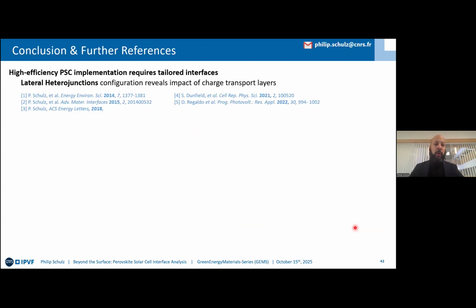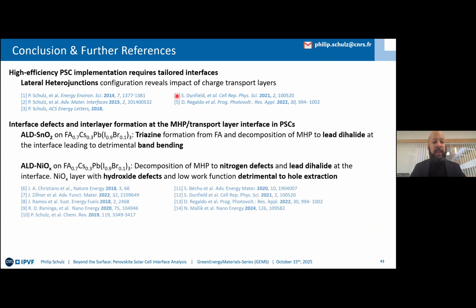To conclude, today we were talking about high efficiency, so the need for tailored interfaces to implement perovskite solar cells. We have this lateral heterojunction platform that reveals the impact of charge transport layers, and that we now use as an experimental platform to check different interlayers. We were looking into interface defects and interlayer formation of this halide perovskite transport layer interface in perovskite solar cells. When you deposit ALD tin oxide on top, we find this triazine formation from formamidinium and decomposition of the metal halide perovskite into lead dihalide, which is then going hand in hand with some suggested band bending.